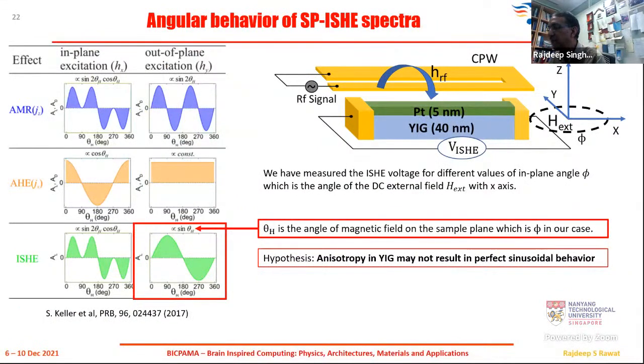Now, what we did again is that we again have a phi scan. That means the external magnetic field is rotated in the XY plane. And we observed once again the VISHE, how it is varying as a function of this change in angle phi. Now, what is given in the literature, which is basically listed over here, and not only this, but many other things, is the variation that is expected when you have an out of plane excitation, because I mentioned in our case, the HRF is perpendicular to this. So we are actually dealing with this case. The variation in the ISHE is expected to be fitted by this sine curve. Okay, and that basically comes because of the measurement geometry. Nothing else. So in this case, the so-called magnetocrystalline anisotropy effects were not basically investigated.